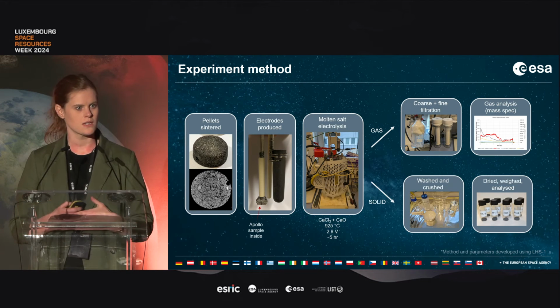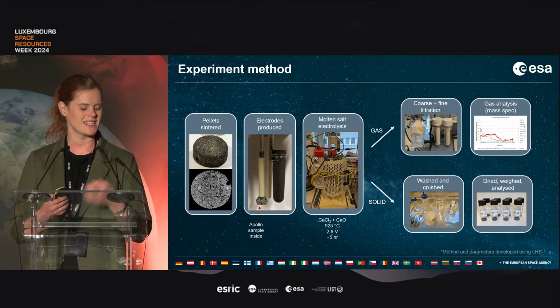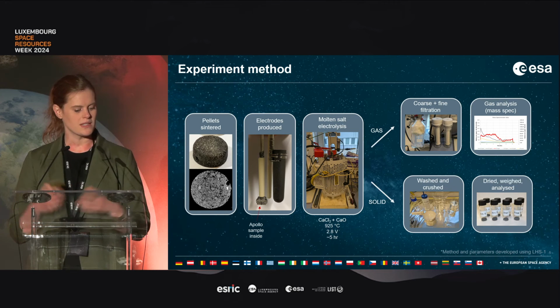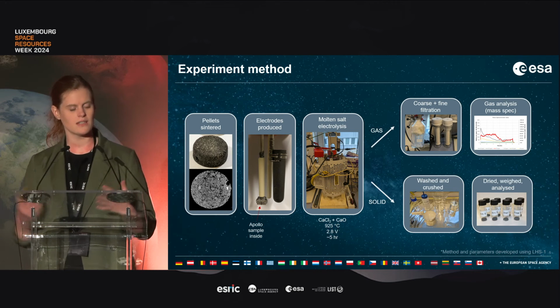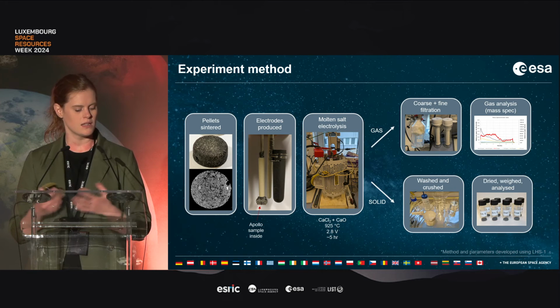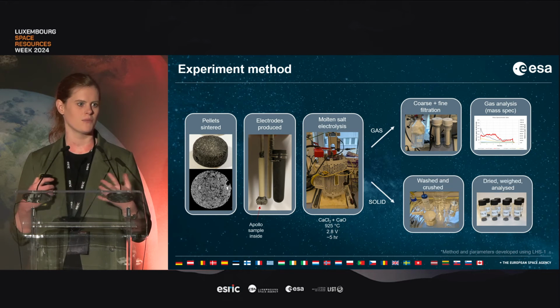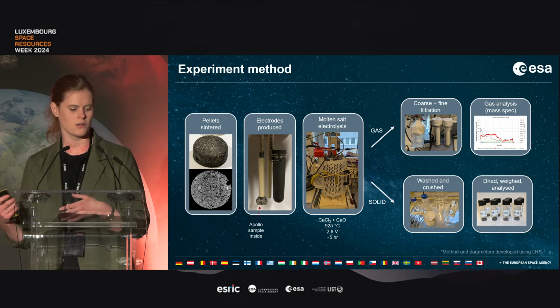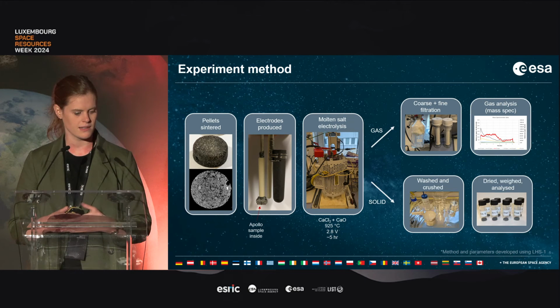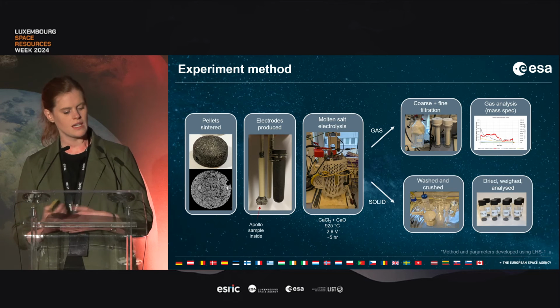We cycled through a range of different options for this kind of miniaturized basket. And what we settled on was not necessarily the most efficient, but it was the best balance between efficiency and protecting the material, because the thing we were trying to avoid mainly was losing the material before the reduction had actually taken place. For this experiment, we chose to use carbon anodes.